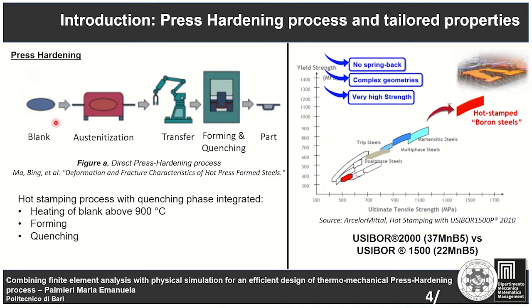A scheme of the press-hardening process is shown in this image. In particular, a blank, typically in high-strength boron steel, is heated for approximately 5 minutes at a temperature greater than 900 degrees to obtain an austenitic microstructure. After, this blank is transferred to a cooled stamping die, and after the forming phase, the part is quenched within the die. The cooling rate must be greater than 27 Kelvin per second in order to obtain a martensitic microstructure that gives the component high mechanical resistance.